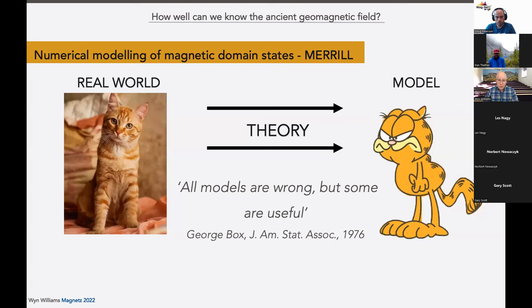We've gone to great lengths to try and verify our models, and I'll show you just a couple of examples. This is a grain of magnetite along with this off-axis electron holographic image on the right-hand side in some work I did with Trevor Almeida some years ago. And on the left-hand side is our reconstruction of the grain and the simulated off-axis electron holographic image. And I think that shows a remarkable resemblance to that of the real grain. Some other work that I've done here is with Evgenia Karpova from the IRM in Minnesota, who produced these amazing magnetic force microscope images of a large TM54 grain.